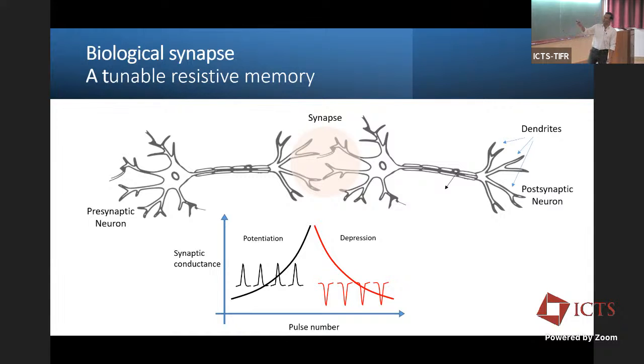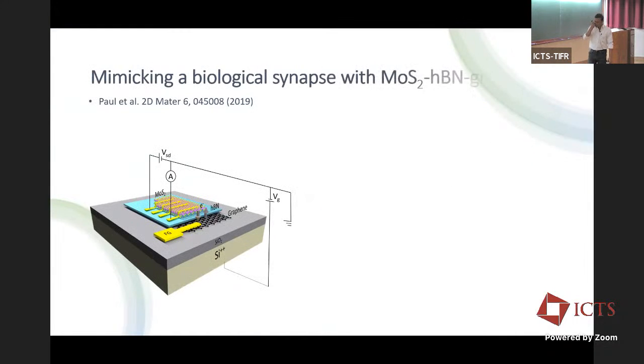Now, using these molybdenum disulfide based transistors, we could mimic the synaptic activity quite nicely. This work has suddenly become very popular. When we did it, we didn't really think it would be interesting. We just thought it's fun. So we have a layer of molybdenum disulfide sitting on the surface, and there is a charge storage layer of graphene, which is below an insulating layer of boron nitride. The blue layer is like a dielectric, which separates the electrically conducting channel from a charge storage layer, which is graphene. So all we have done is, by applying a voltage pulse on this back gate, we either take charge from the top layer to the bottom layer and store it there, that changes the electrical conductivity, or by applying an opposite pulse, we take charge out of the storage layer and put it back into the top layer,